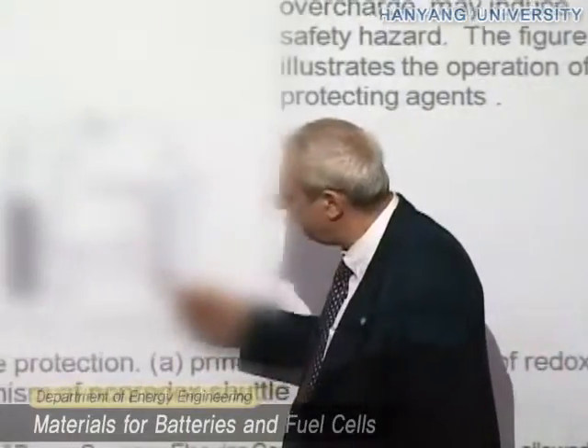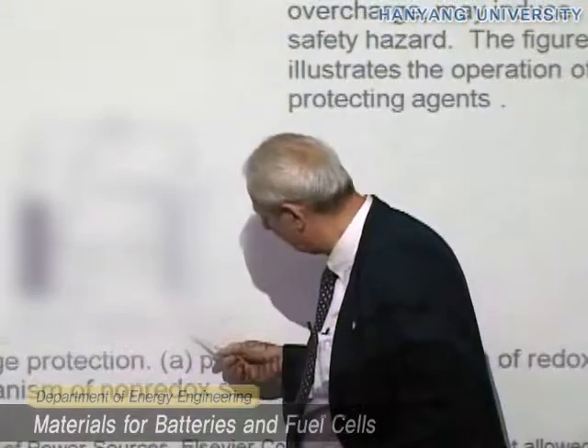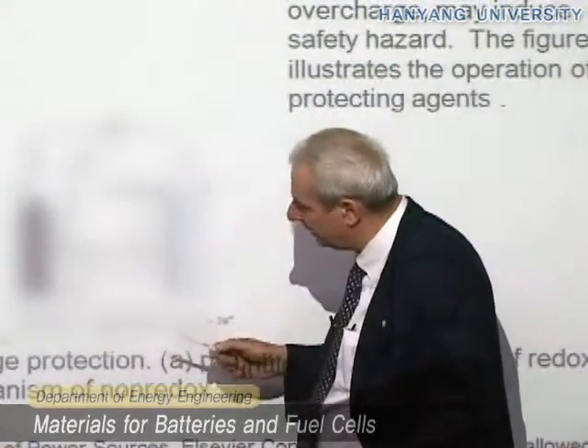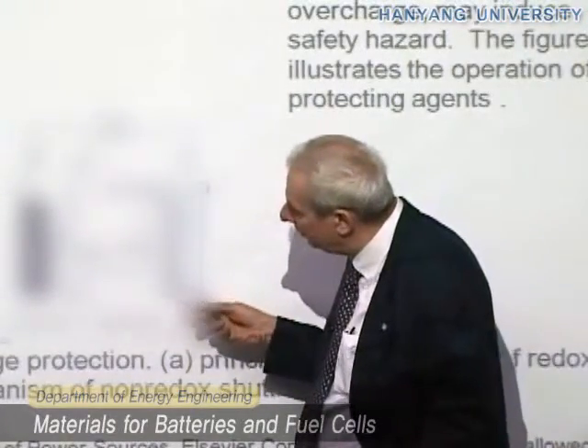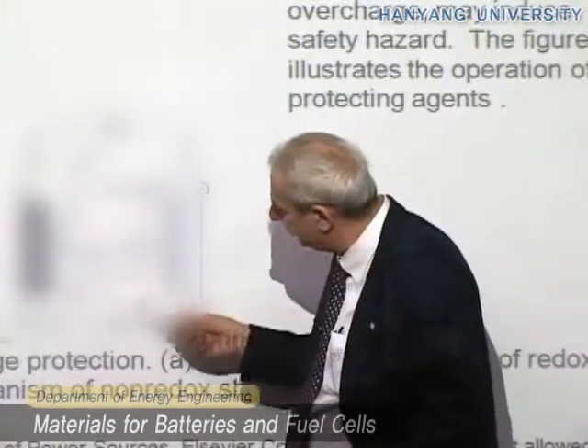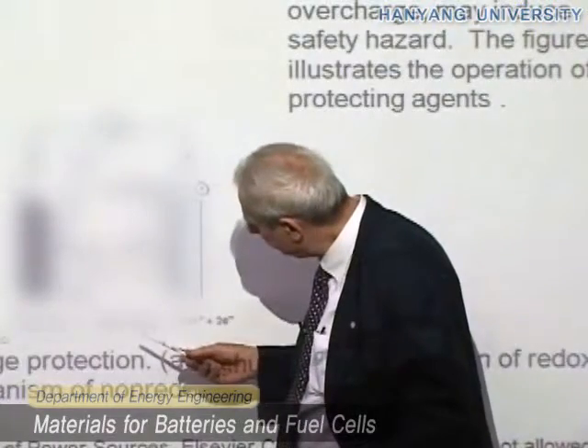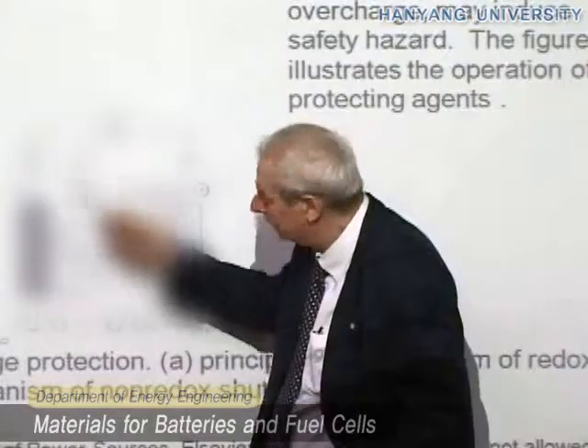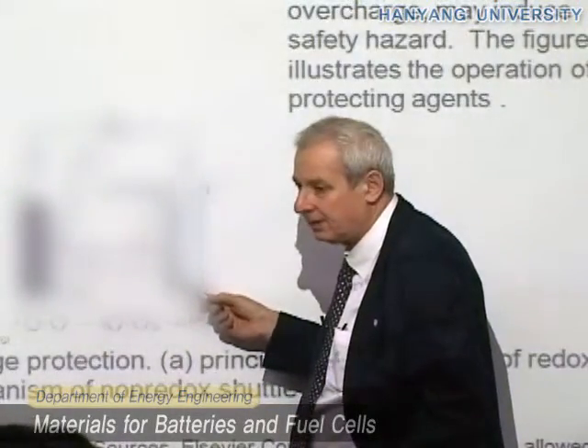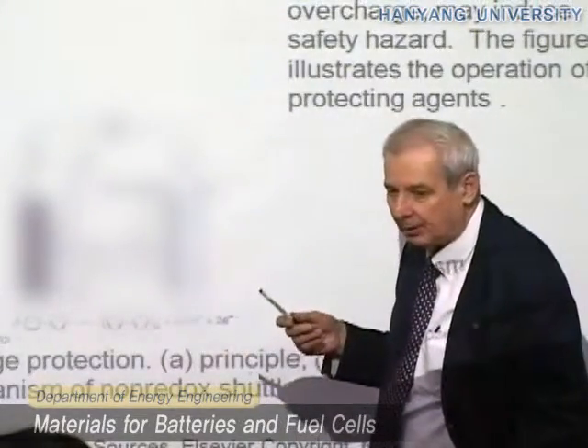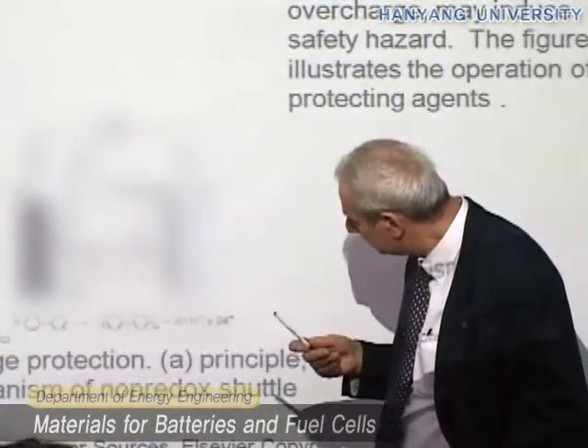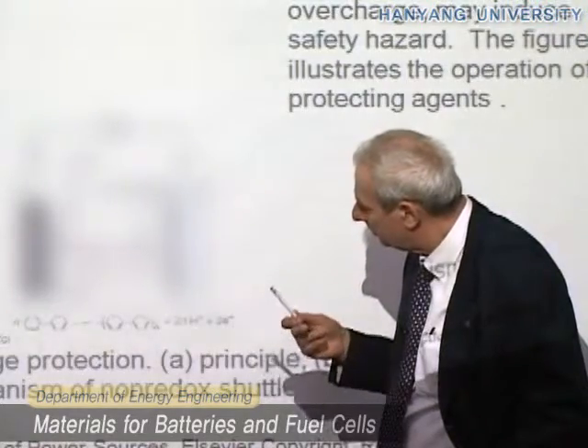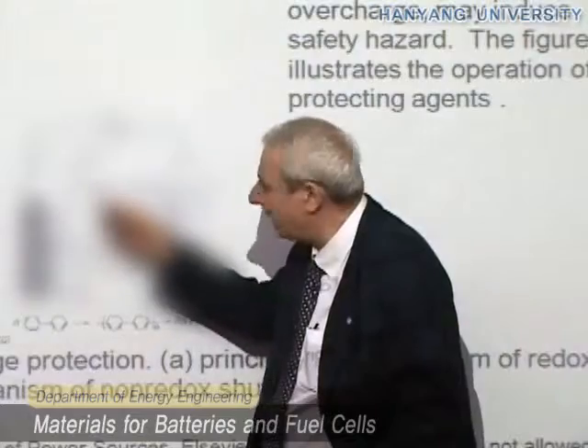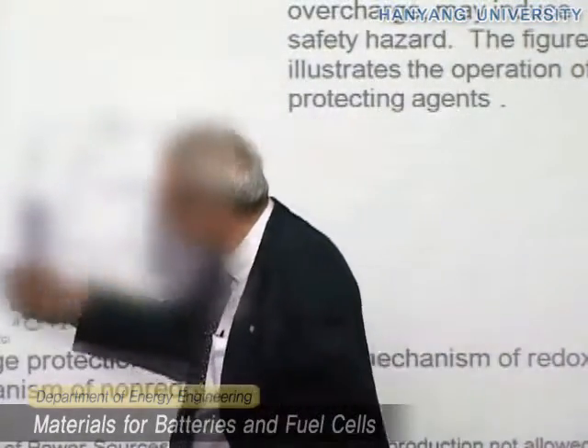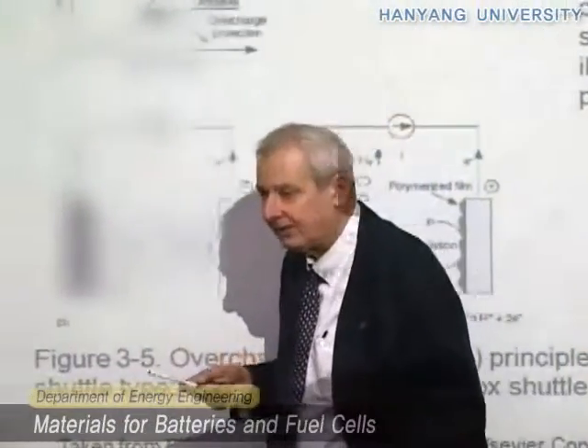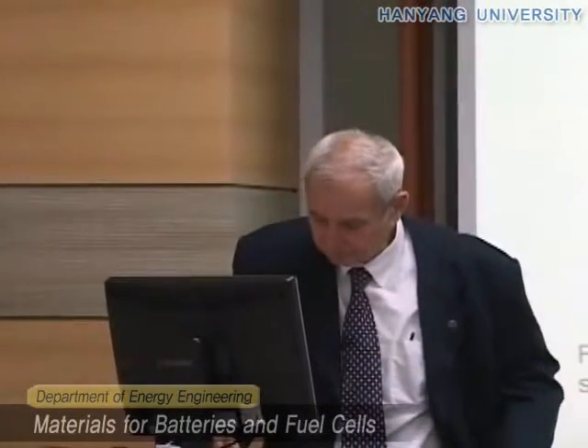In this other case, instead, you may have a situation, here is indicated the reaction. Sorry, I didn't realize that. Some organic material. So here instead, what will happen is that you will have at the negative electrode some reduction, for instance, of some hydrogen reduction. So hydrogen will be evolved. And at the other, you have some oxidation. So in this case, you decompose, you consume your shuttle component. And this is not a good idea, though, because you form some hydrogen here, which may be also very dangerous, and some other material. So the best shuttle are these ones. And these are widely used now in practical batteries.